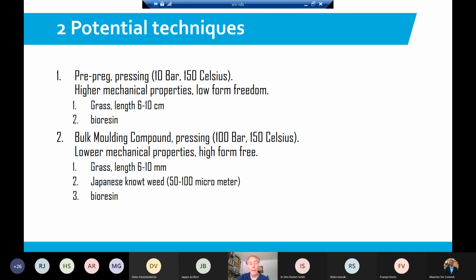You have lower mechanical properties than the pre-preg method, but you have very high form freedom. So you can make ribs in your product to reduce the amount of material. For this technique, we need smaller grass fibers, 6 to 10 millimeters. So that's much smaller. And we can combine it with Japanese knotweed or another filler, but we chose to use